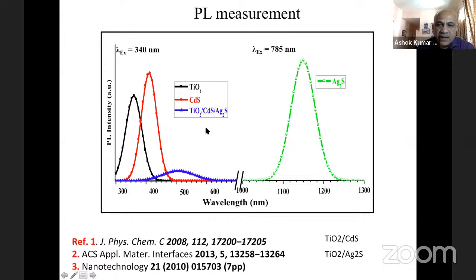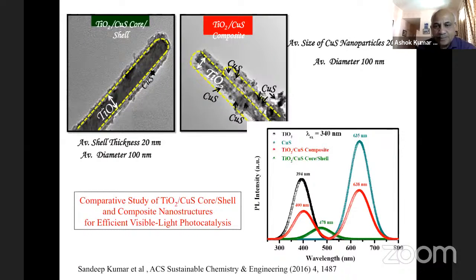It is even higher than if you make just one core shell, as has been reported earlier. That means you have two shells with a proper design, of course, which should be based on the energy levels of those semiconductors. You can get much lower photoluminescence, and that means higher lifetime of the charge carriers.